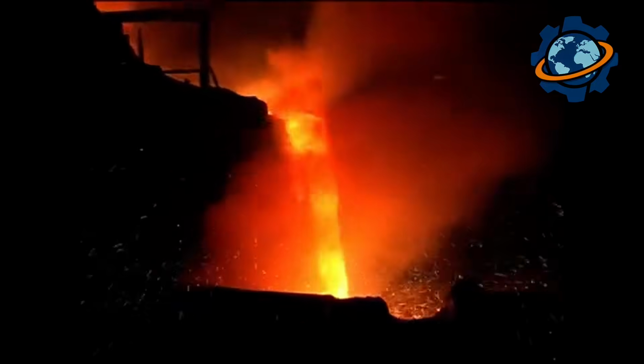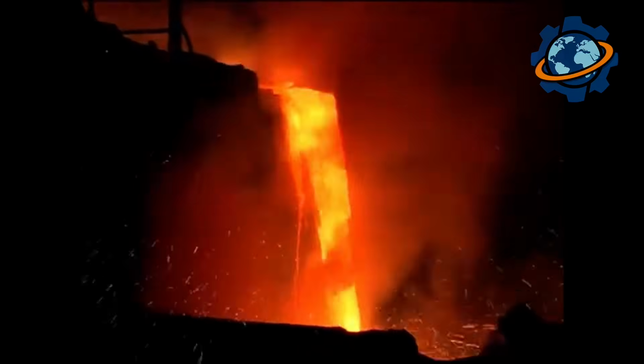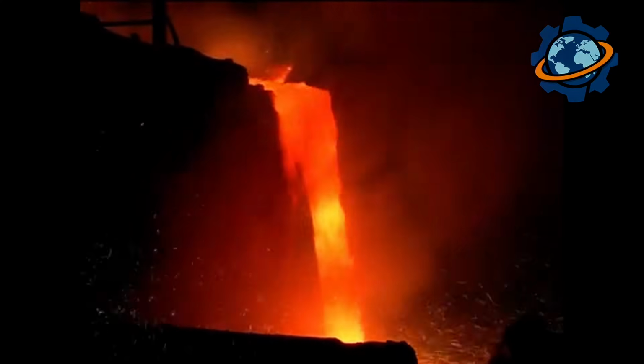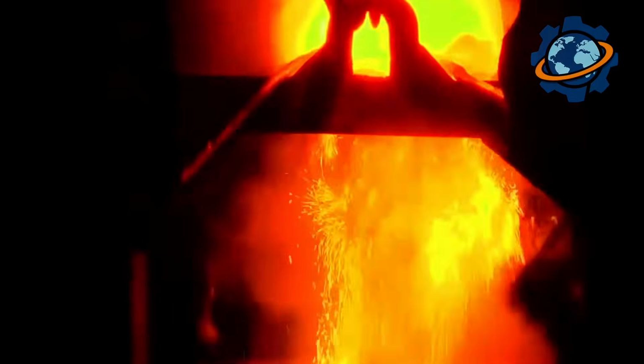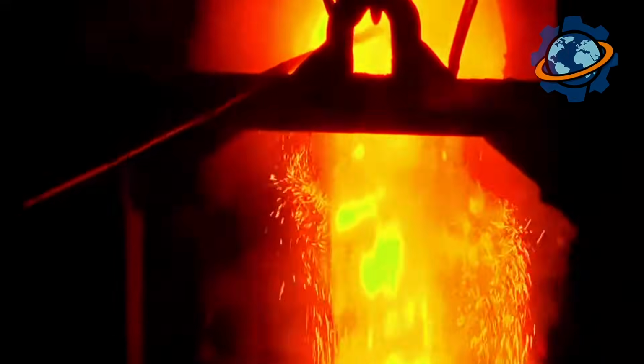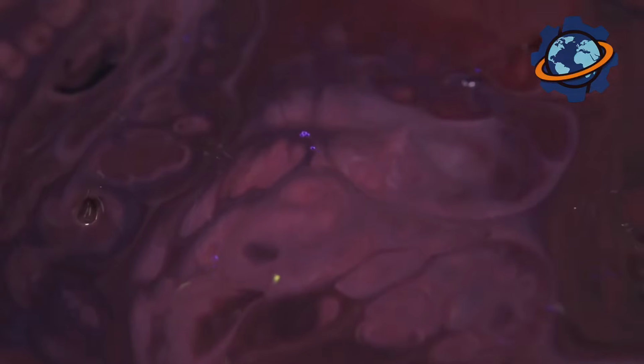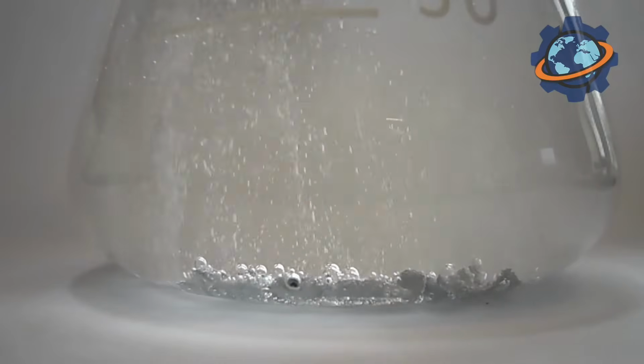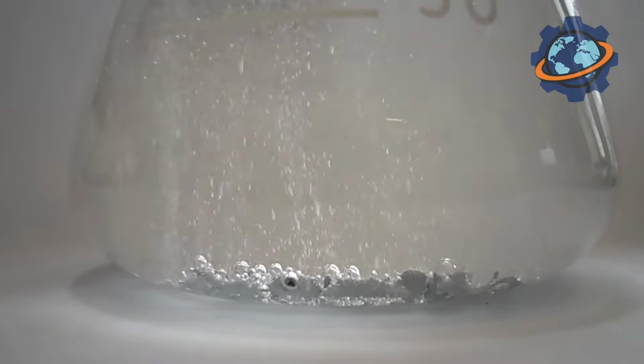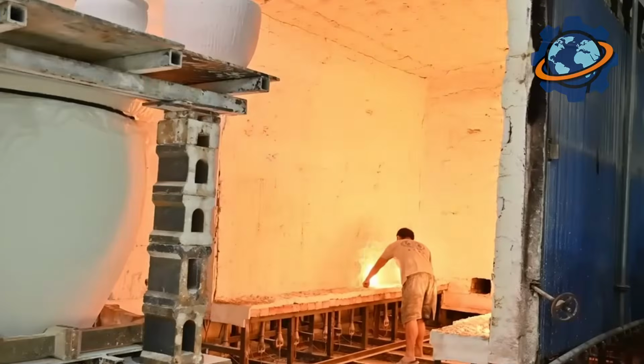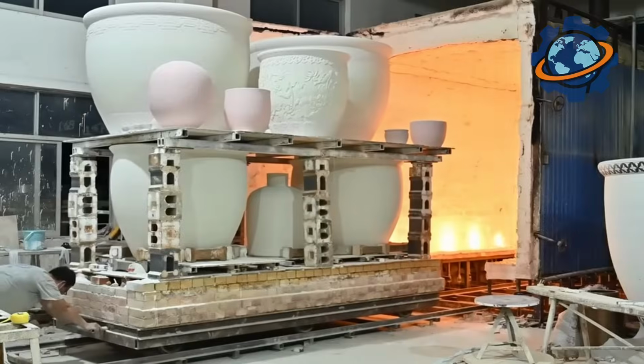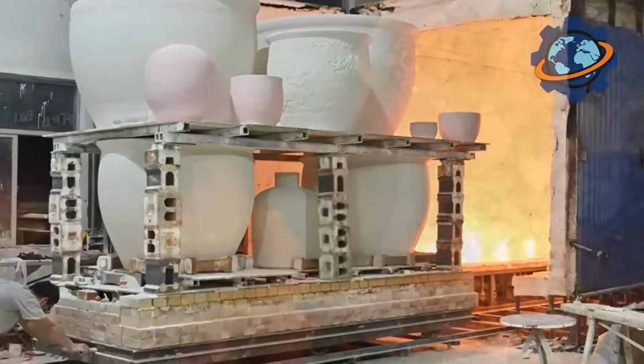At such temperatures, complex chemical reactions are triggered, mineral particles soften on the surface and sinter together, forming a strong and dense ceramic structure. In the system of aluminum oxide and silicon dioxide, new crystalline compounds are formed, in particular, needle-like crystals of mullite, which, like reinforcement, permeate the entire structure of the brick, giving it exceptional strength and thermal stability.